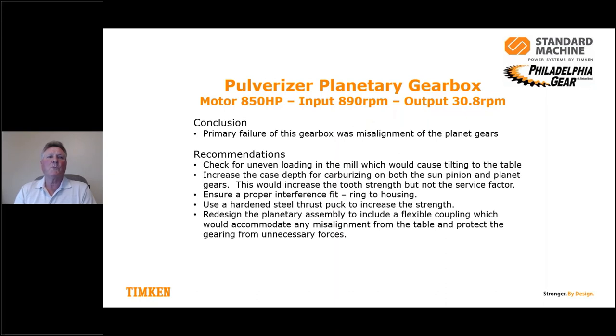So what were our recommendations? We need to check for uneven loading in the mill, which would cause this tilting of the table above the gearbox. We could improve the gearbox by increasing the case depth of the carburizing on both the sun and the planet gears, which would increase the tooth strength, not the service factor, simply the tooth strength. And we would make sure that the proper interference fit from the ring to housing was done at the assembly stage. Using a hardened steel thrust puck would definitely help.